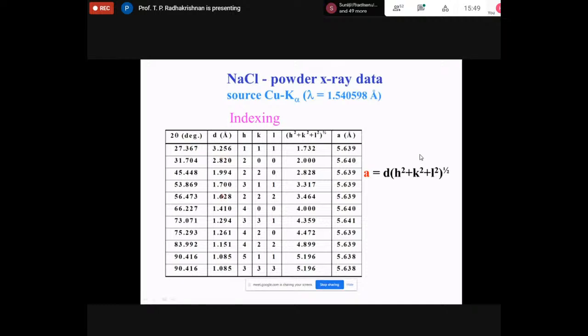Now, this is the only raw data from the experiment. Now, what do we do? h, k and l are integers. If you remember, I mentioned these are integer values. By definition, the Miller index is hkl. In principle, it can start from 100, 110, 111, and so on as integers. Now, you go on trying different values of indices, integers, and try to use this equation. For example, this is the equation for the cubic group. If I take various values of hkl and know the value of d, I can calculate a. I go on doing this for various possible hkl values and various d's and do an exercise to see if I will always get the same value of a.